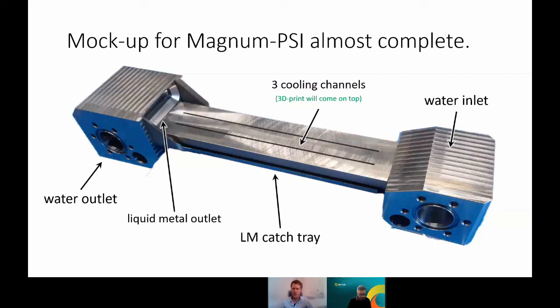But if this 3D printed tungsten already has some kind of microporosity to begin with, so I'm talking about really the printed bulk, not the intentional porosity that we print in it, but really the porosity in the bulk, which is also there, you might use that actually to your advantage. Maybe this is fine enough for helium bubbles to escape. I'm not sure actually, but that is a thought I would have.